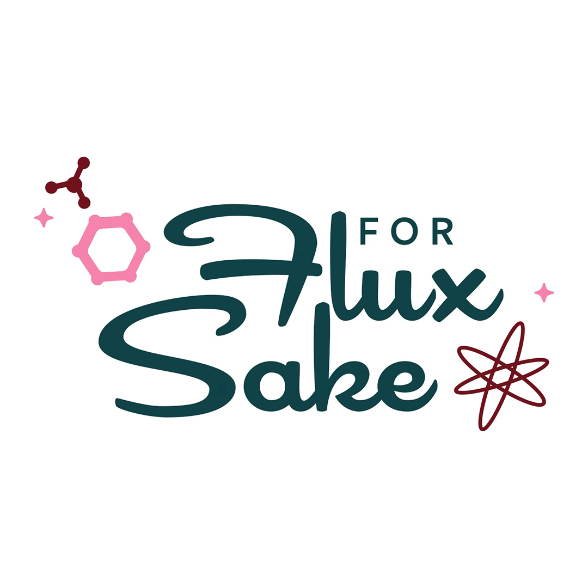But we end up in this terrible place where the mid-temperature world claims that the glazes are cone 5-6, or mid-temperature, and they literally are not. Do all glazes have a range? This is going back to Lena's question. Glazes have a range, but that means maybe one cone plus or minus. If your glaze is going to be overfired at cone 5, by the time you get to cone 6 it's going to be a disaster. And if it's perfectly fired at cone 6, at cone 5 it's going to be underfired. It's kind of irresponsible to be selling glazes with this sort of range and just saying, do whatever you're going to do. And that's a real problem.